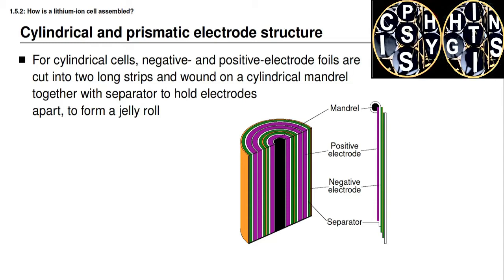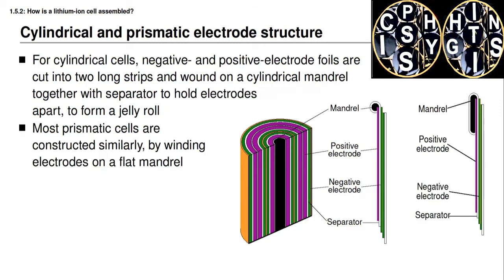center, actually. The electrodes ultimately end up with a structure that's shown on this diagram, where you can see that a spiral forms from concentric layers of negative and positive, negative, positive, all separated by the separator materials. The prismatic cells are constructed in a very similar way, but the winding is done around a flat, thin flat mandrel instead of around a cylindrical mandrel, which makes for an overall flatter package that's inserted into a prismatic can